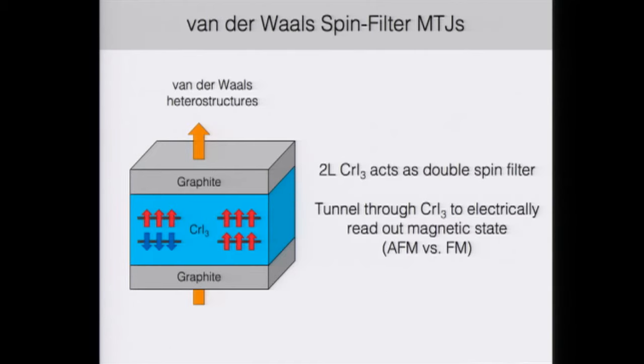So we then adapted this idea to the van der Waals case, where we can use two graphite layers as the non-magnetic electrodes. And due to the van der Waals nature of chromium iodide, we don't need to use a spacer layer because the van der Waals gap will actually just serve as this decoupling between the two layers, say in a bilayer flake. And so we should, in principle, be able to treat bilayer chromium iodide as a double spin filter and then be able to read out electrically whether we're in the AFM or FM state as we apply an out-of-plane magnetic field.